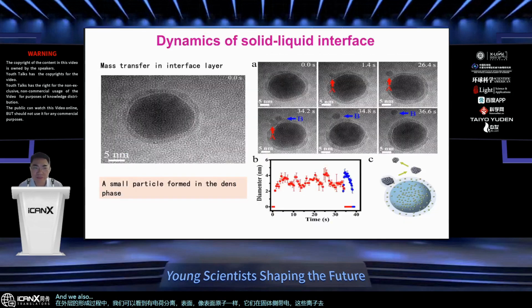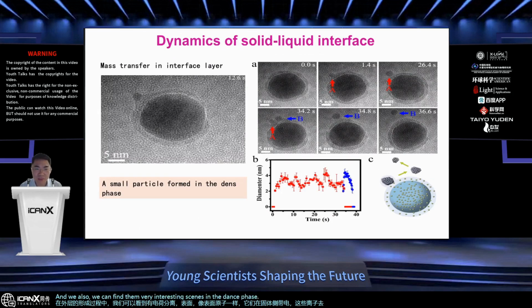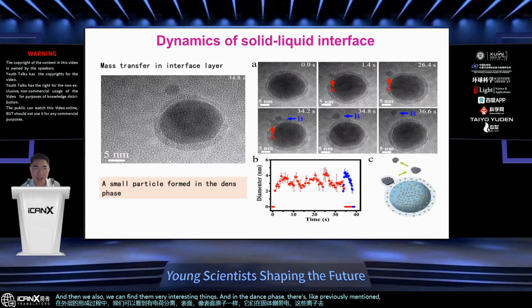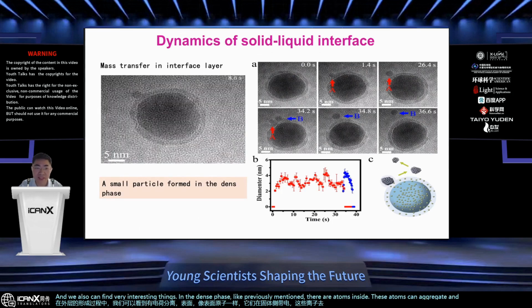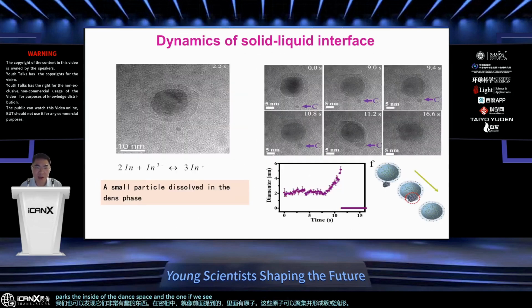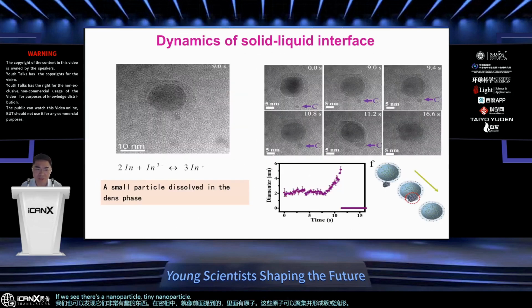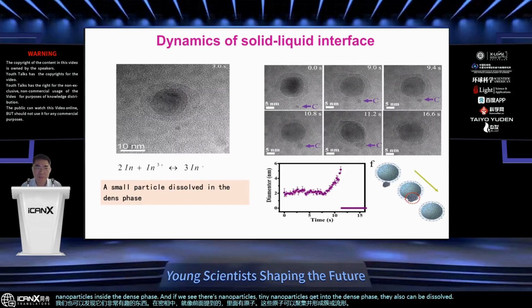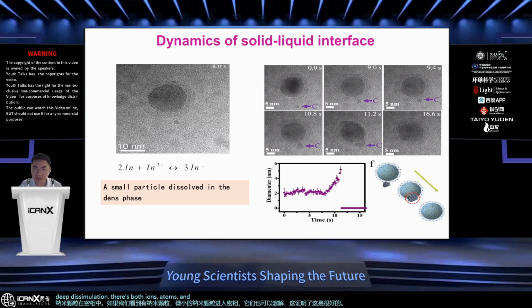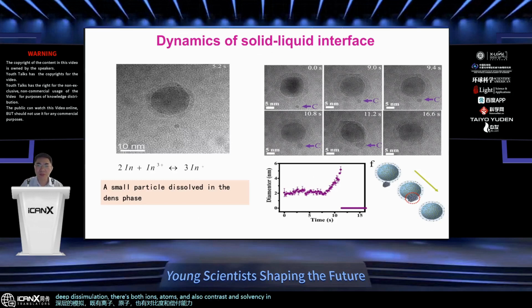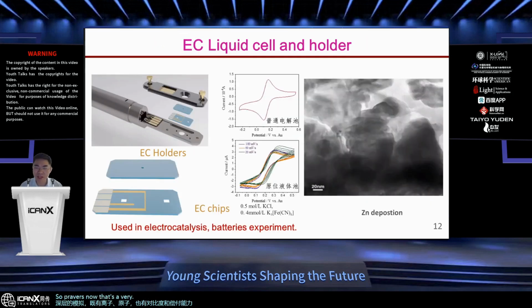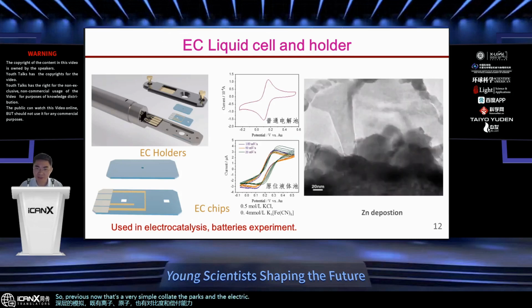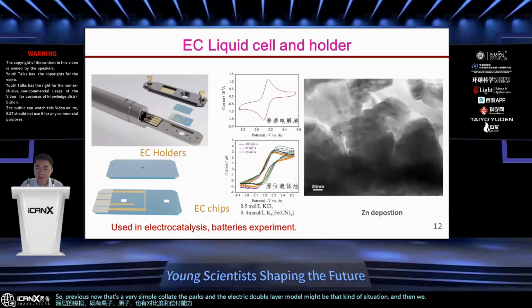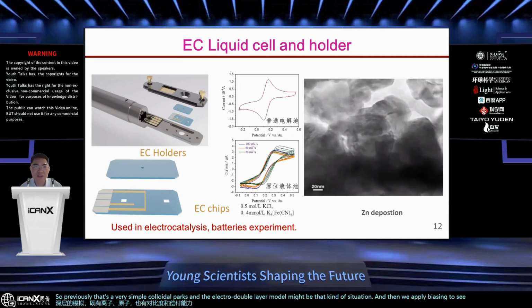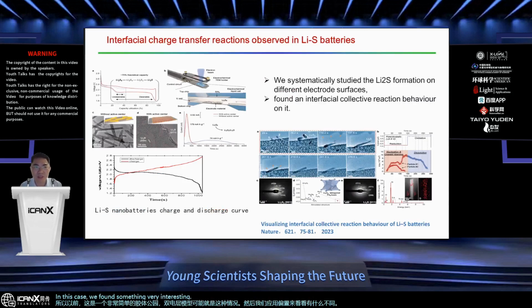And we can find very interesting things. In the dense phase, as previously mentioned, there are atoms inside. These atoms can aggregate to form clusters or nanoparticles inside the dense phase. And if tiny nanoparticles get into the dense phase, they can also be dissolved, which proves the previous DFT simulation that there are ions, atoms, and also counter ions and solvent inside. So that's a very simple colloidal particle, and the electrical double layer model might be that kind of situation. And then we apply biasing to see what's different. In this case, we found something very interesting, what we call interfacial charge transfer reactions observed in lithium sulfur batteries.